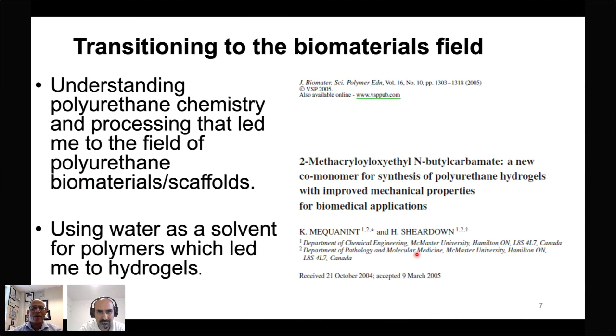The second important thing that came out of this is the fact that I was able to use water as a solvent in polyurethane chemistry and the processing of the thin films. Then that led me eventually to work with hydrogels. Of course, as you all know, hydrogels are materials that are cross-linked, and then they are swollen in water. And so those are the two messages that really came out of that. And in fact, when I moved completely to the biomaterials field, one of the earliest publications that I had from one of my postdocs was this combination of the polyurethane chemistry and the use of water as a medium to design polyurethane hydrogels with improved mechanical properties for biomedical applications, and that was published in this journal back in 2005. Although the work was done 3 years prior to this particular publication.